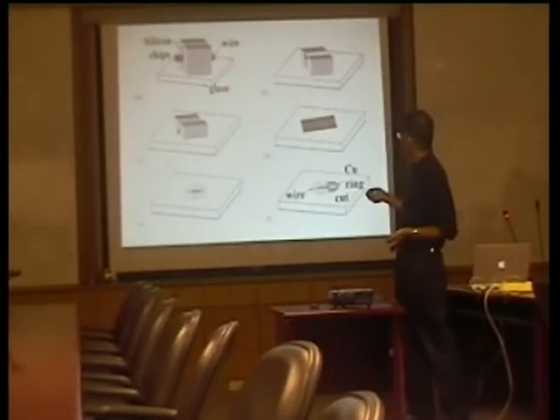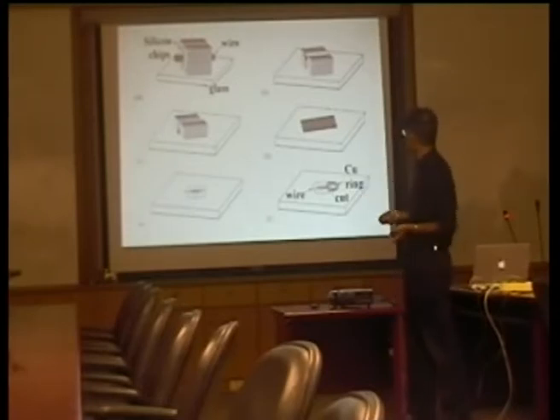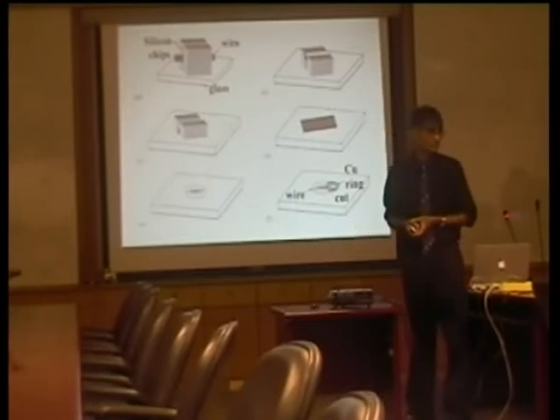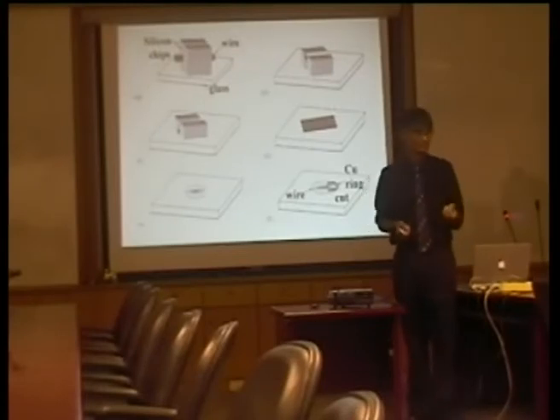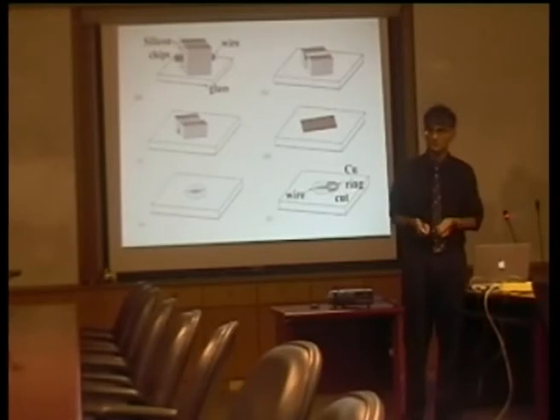They've put the wire between two chips of silicon, okay, and then sectioned it so that you get a flat section of the wire, cut it, and then simply ground it down to produce a thin enough specimen to do transmission electron microscopy. Very, very clever method of preparing a specimen for transmission electron microscopy. First time certainly that I have come across it.